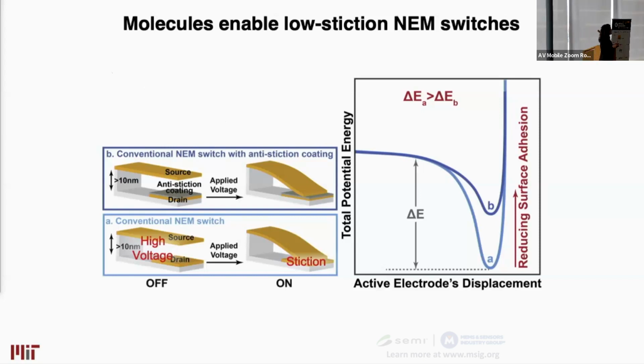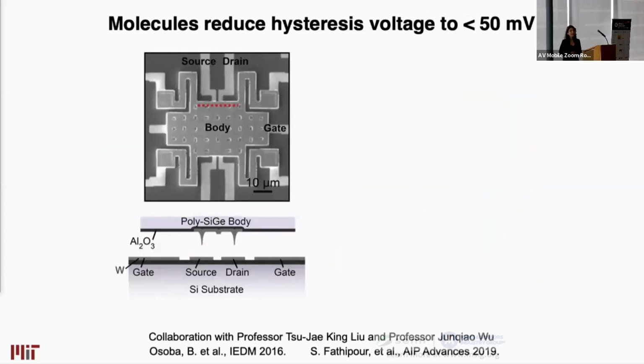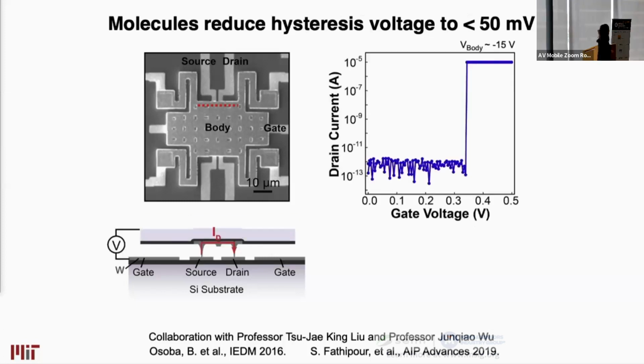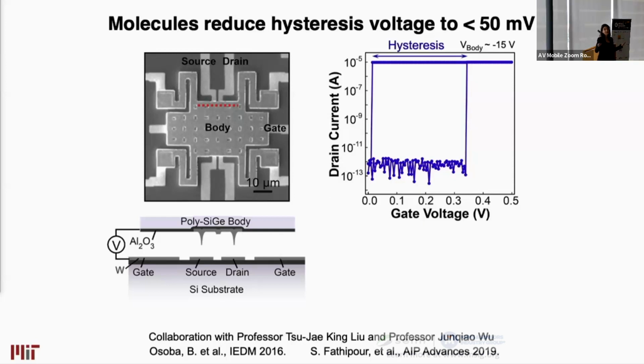So by being able to integrate these molecules within electromechanical devices, we can lower the surface energy and, as a result, lower the adhesion experienced between the contacts. So here I'm showing you a scanning electron microscope (SEM) image of a MEMS relay. This is micron in size. So the cross section here shows you how you have a top membrane separated from the bottom source, drain, and gate. An applied voltage causes the membrane to collapse, turning on your device. And as the voltage is removed, you get recovery. And of course, as expected, because of surface adhesion, this is associated with a hysteresis in operation, which sets a limit on how energy efficient you can make this device.